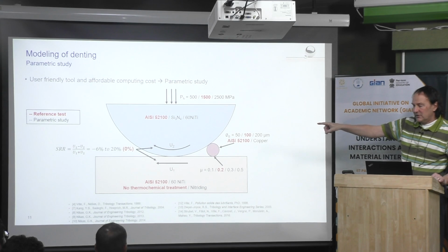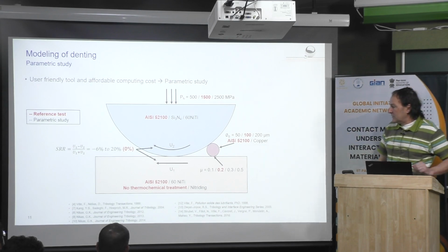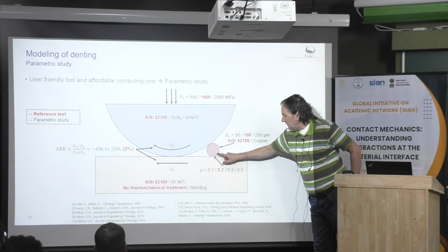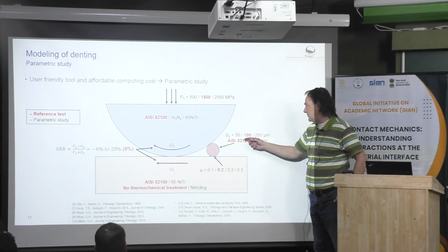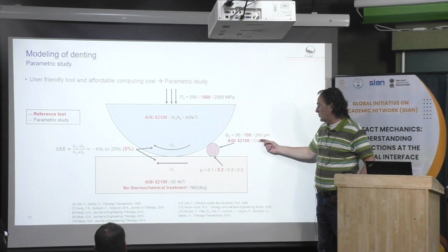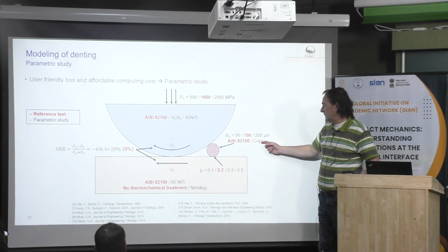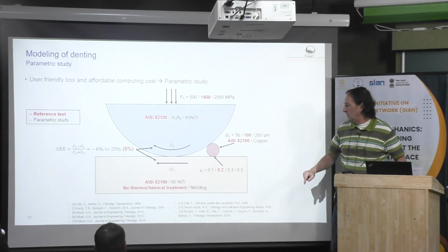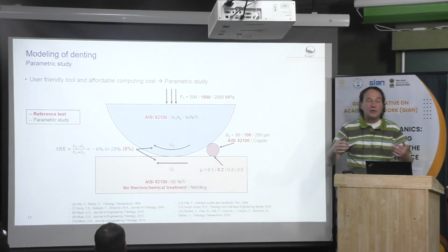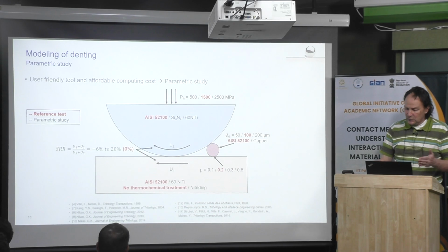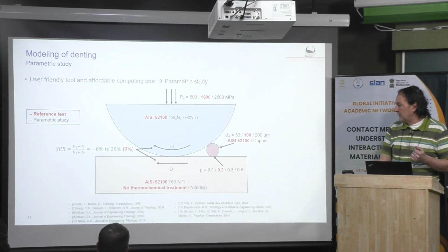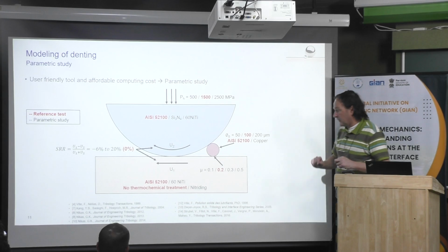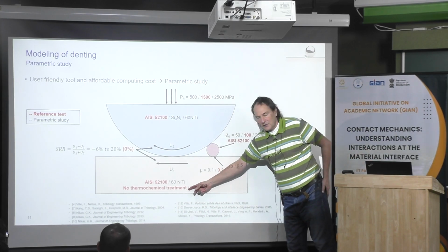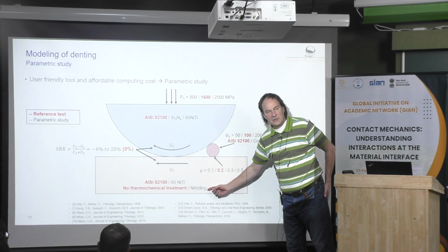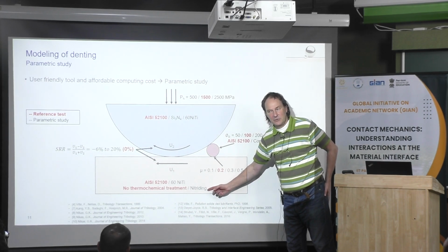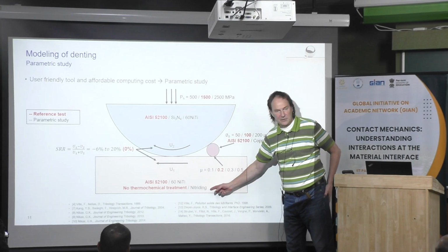20% is quite high for sliding. Okay, and then also we change the friction coefficient at the interface, and we will use particles of different materials, M50 or copper, which is softer than steel. Okay, and size 50, 100, and 200. When it is in red, it corresponds to the reference situation. Then I will quickly go to that and show you some results. And also, yes, it was without residual stresses or with residual stresses. Then we did consider the effect of surface treatment, here, light shot peening for example.